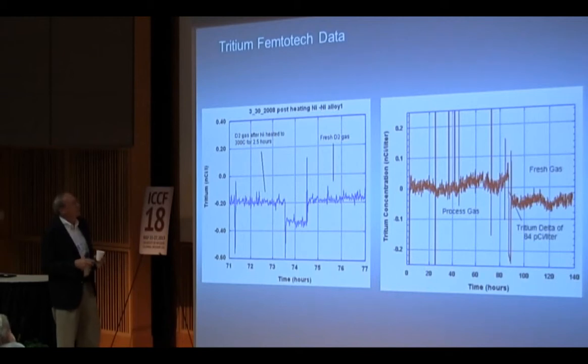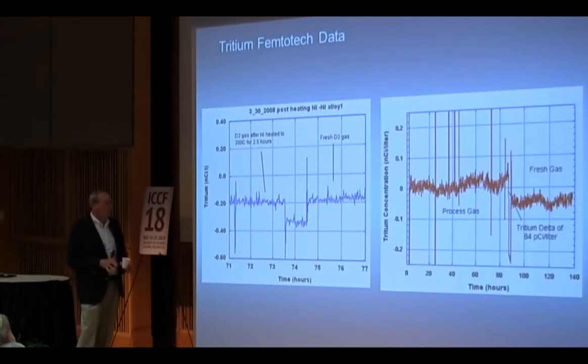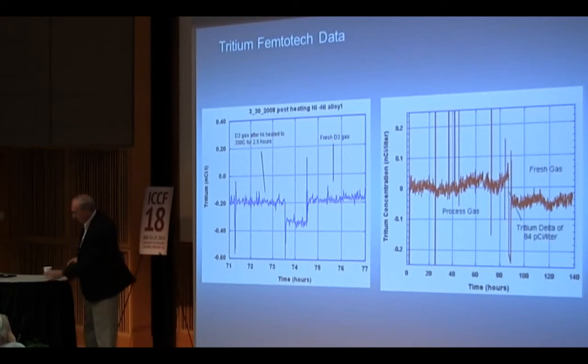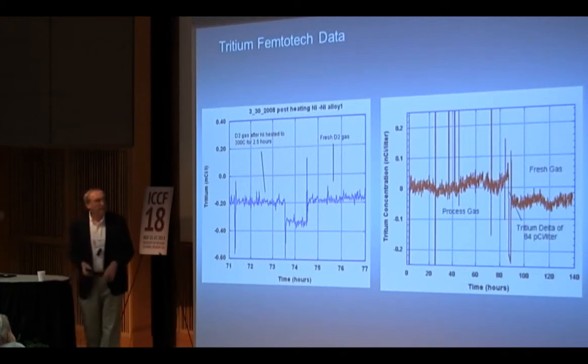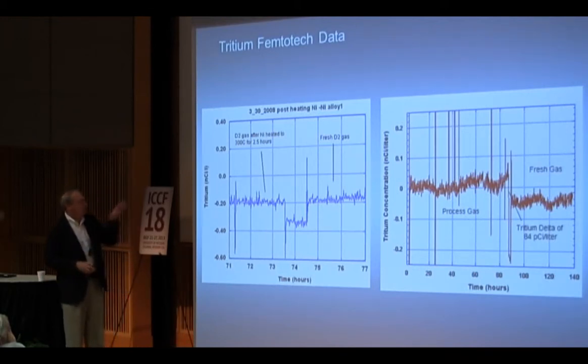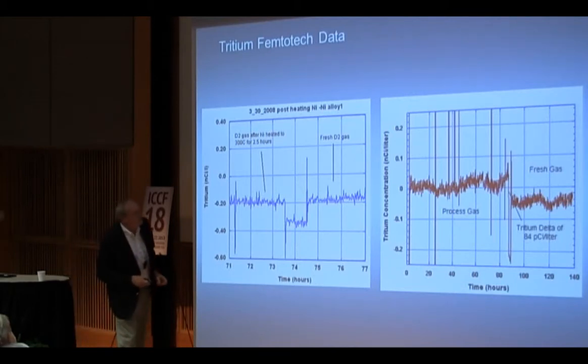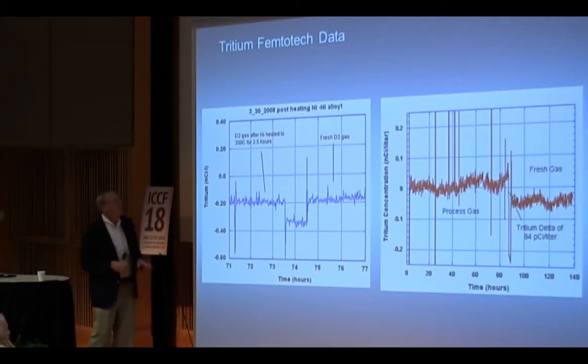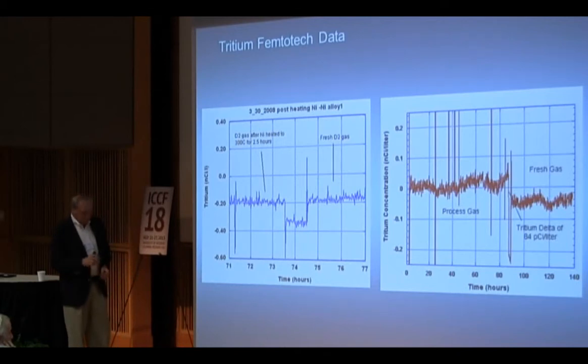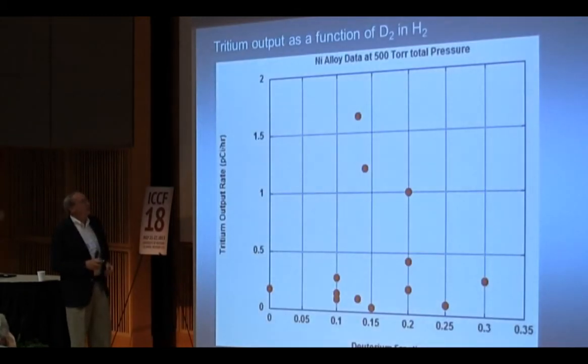I don't want to go through the mechanisms of how we actually detect the tritium, because I think everybody knows what those are. But this is a gas experiment. This is one of these ones where we can run it for a few hours. This one was run for, say, 80 hours. And you can see a delta in the tritium quite nicely. So again, you put that small sample in there, you run it for a day or 2 days or 3 days, and you can get a result.